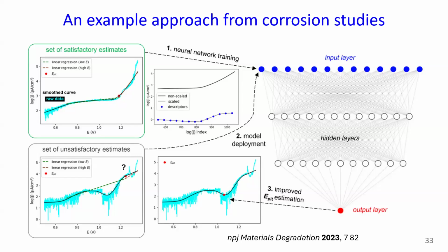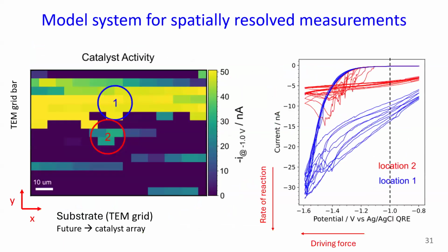However, for more complex voltammograms, ones that don't fit into a more idealized profile, this work develops a neural network trained on good polarization curves in order to estimate the pitting potential of these. That's a way to give us a single-point activity descriptor out of the CV, so that we can, for example, make a plot of activity that's a better descriptor of activity.